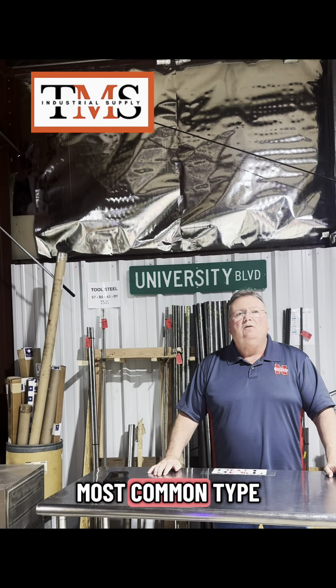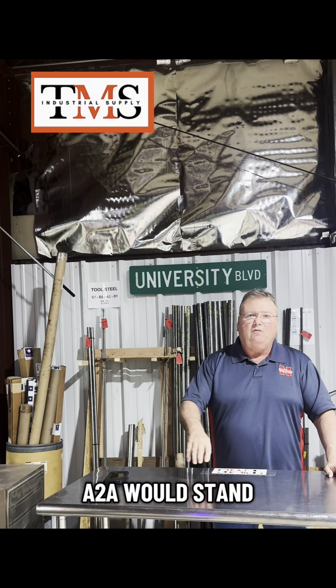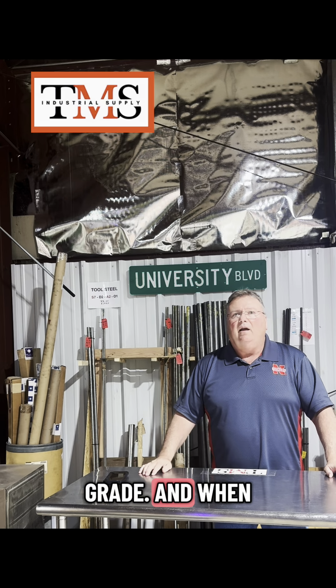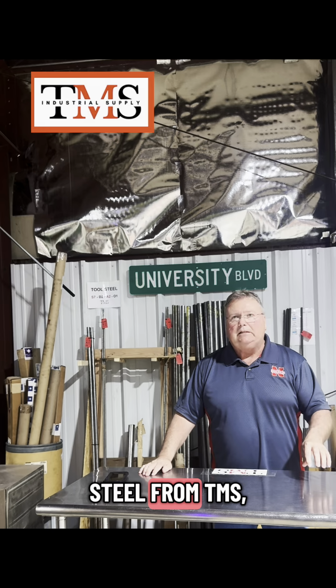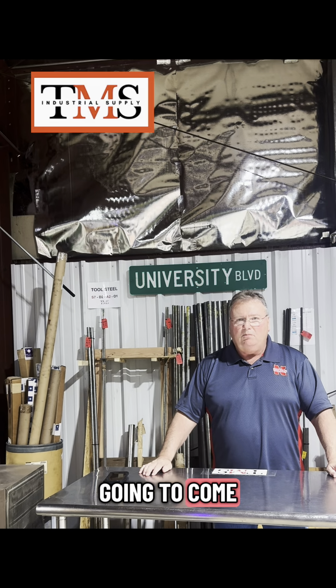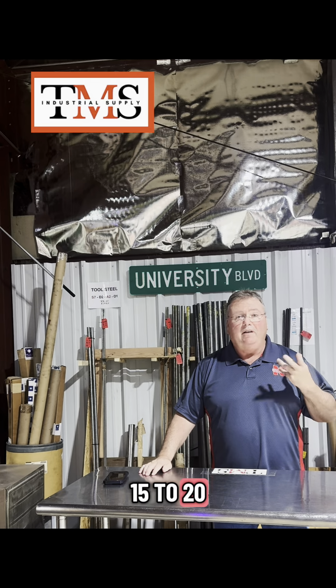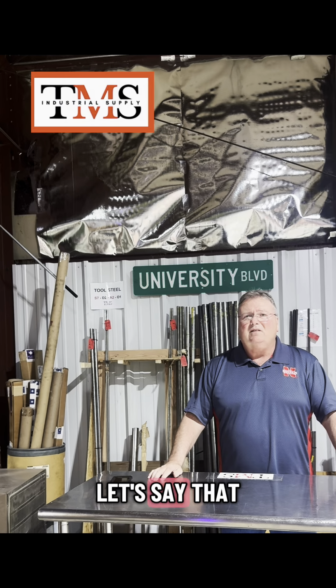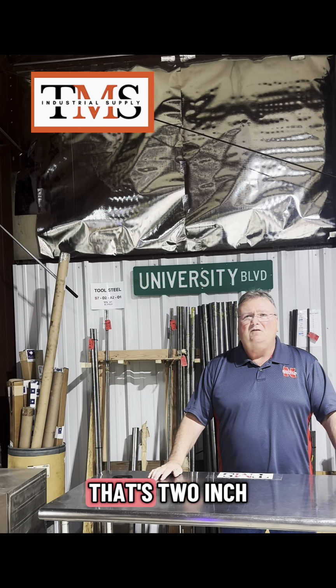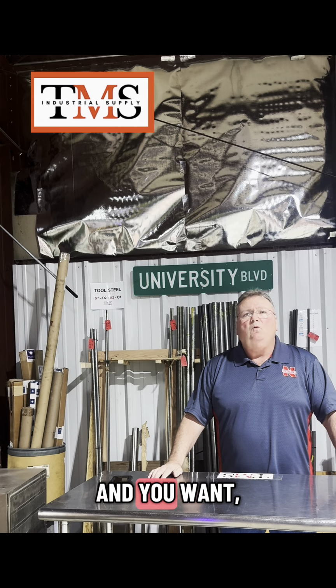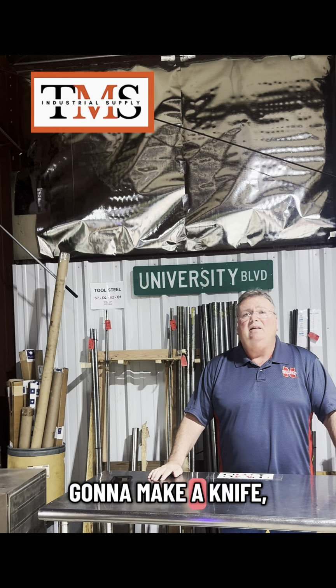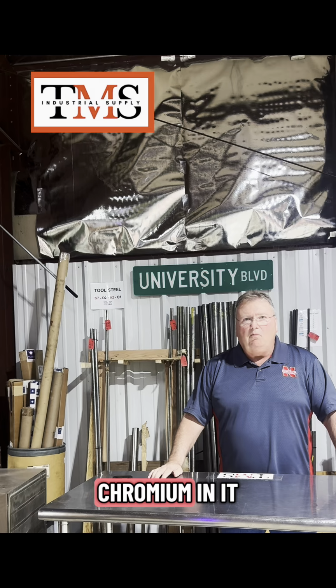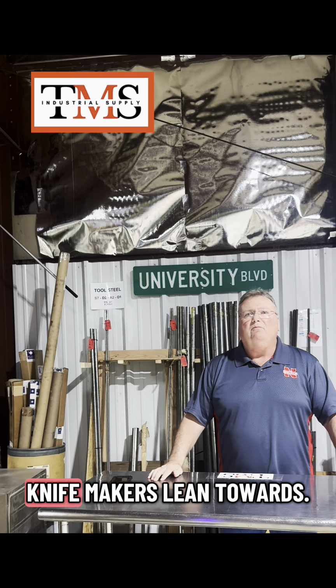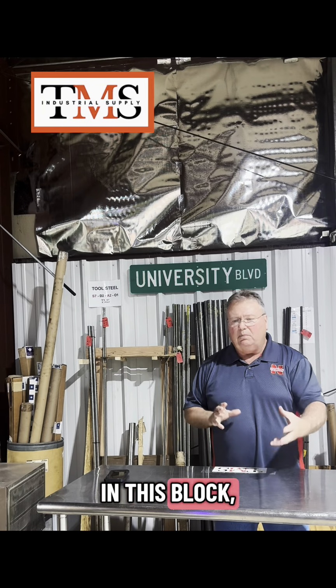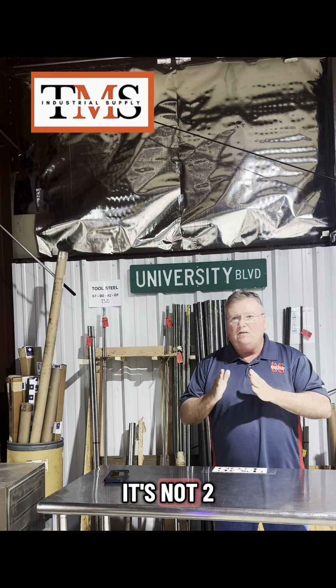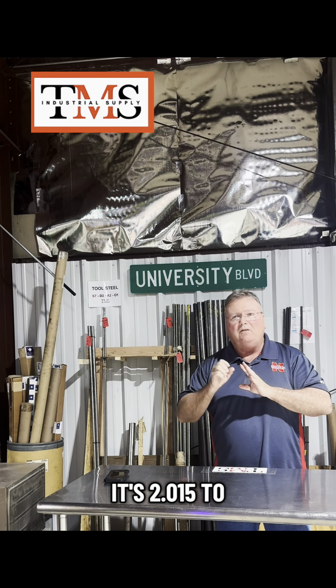The most common type of tool steel is A2. A would stand for air hardening type of grade. And when you're buying tool steel from TMS, this material is going to come to you typically oversized, 15 to 20 thousandths. What that does is, let's say that you, as a customer, want a block of steel that's 2" by 2" by 6 inches long, and you want, let's say, D2 tool steel material because you're going to make a knife. D2 has got a lot of chromium in it, and a lot of moly, so consequently that's what knife makers lean towards. You get this block of steel in, and it's not 2" by 2". It's 2.015 to 2.030 typically.